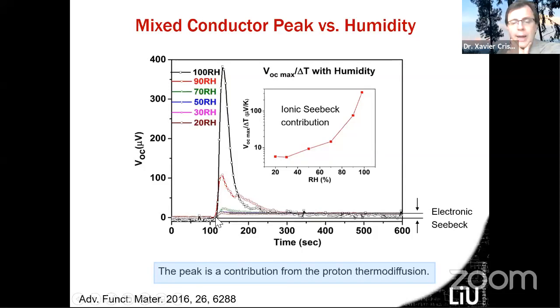For a very dry sample, the ions are not mobile. So what is happening is that you have a small increase of potential here, and you have actually the electronic Seebeck coefficient that you obtain.